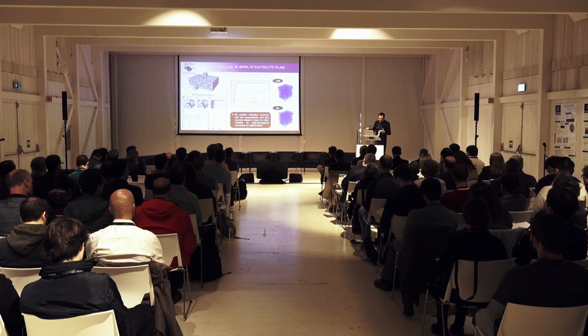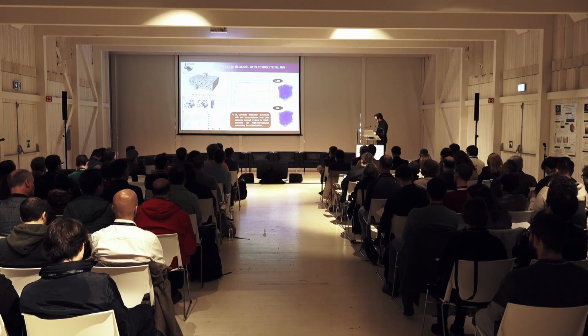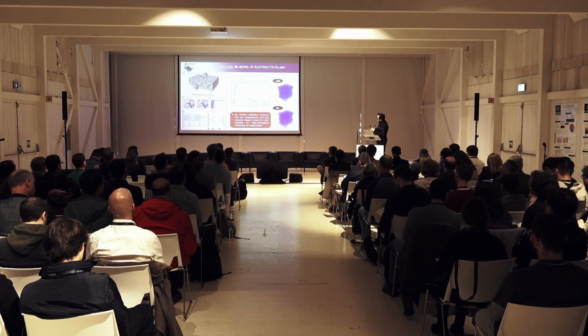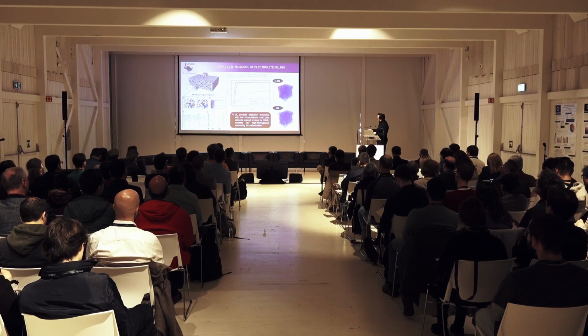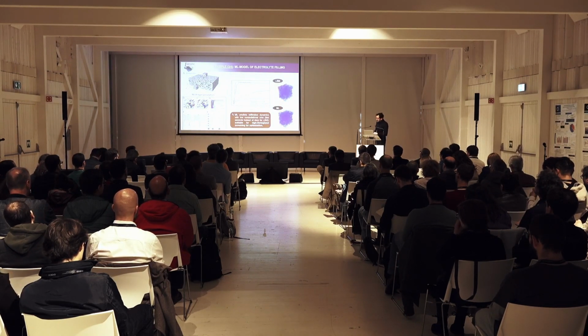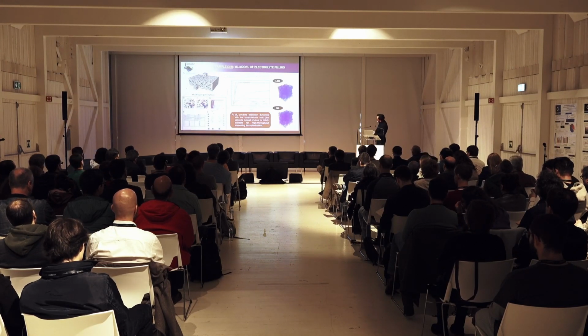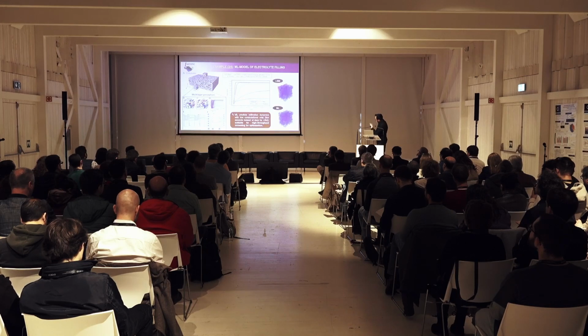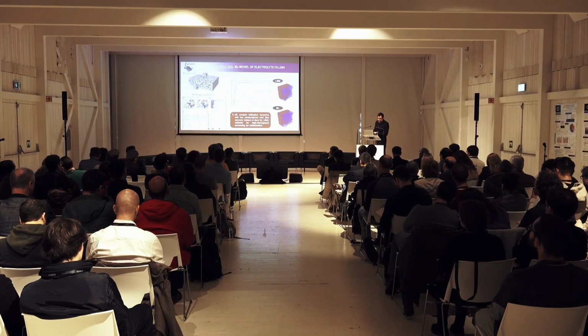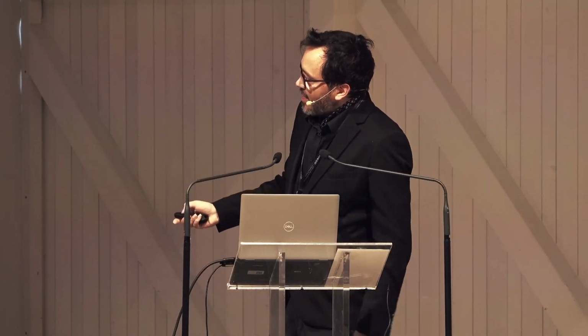It can take you up to one week to simulate the infiltration of an entire electrode microstructure using the lattice-Boltzmann method. So then we decided to use multi-layer perceptron models, more like neural network models, to exploit the data arising from these electrolyte infiltration simulations to make the same kind of simulations as the lattice-Boltzmann method, but much faster, thanks to this machine learning capability. And here now we can predict the infiltration in 3D of the electrodes with the liquid electrolyte in a few seconds instead of a few days, okay? Thanks to machine learning.